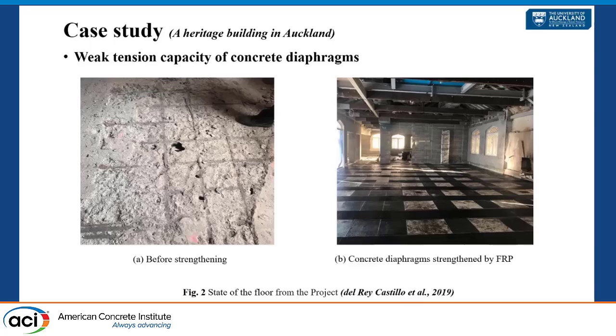floor. And moving to the right, the floor was strengthened in the transverse and longitudinal directions with fiber-reinforced polymer using the EB-FRP strategy. Everything looks much better. The concrete floor surface was repaired and the strengthening capacity enhanced. But what drew our attention here is that in real in-situ construction scenarios, we're often using larger-size FRP, thicker and longer, even 20 meters. But in our research, we only conduct tests at quite small scale, maybe no more than half a meter. So we were wondering if those two have a really big difference in terms of the influence on the overall performance